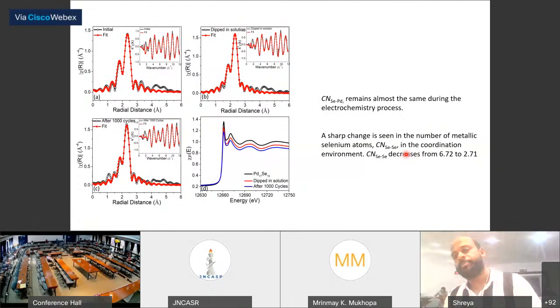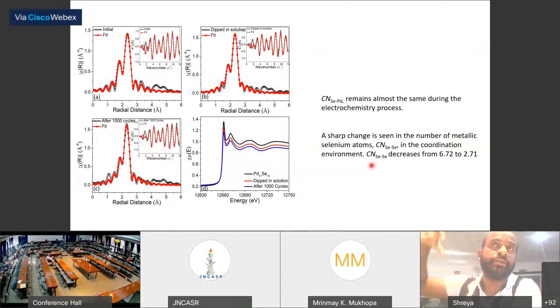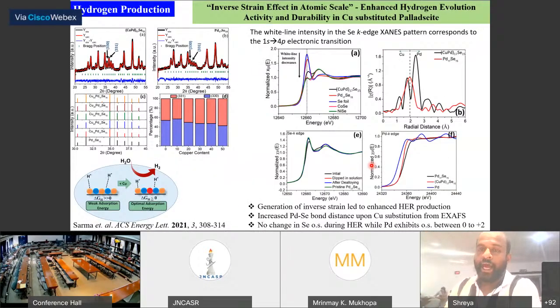I just give the result here: the coordination number of selenium palladium remains the same, and the selenium decreases from 6.72 to 2.71, confirming that selenium is etching into the solution. This we have done under potassium hydroxide. We dipped this electrode in the potassium hydroxide, then took it out and did the experiment, and we found this difference.